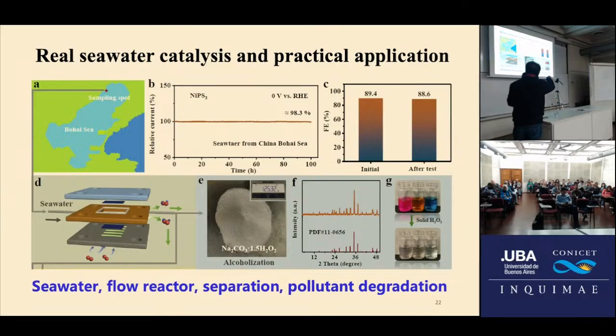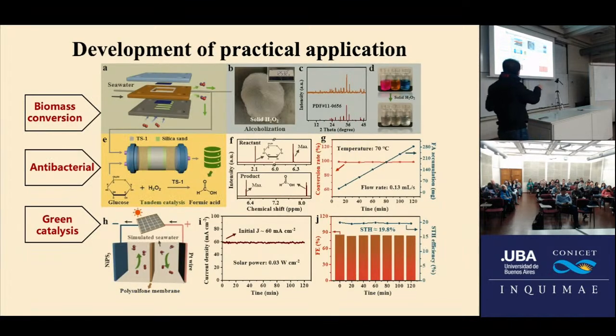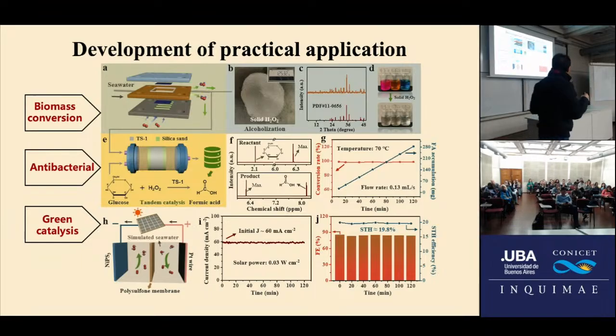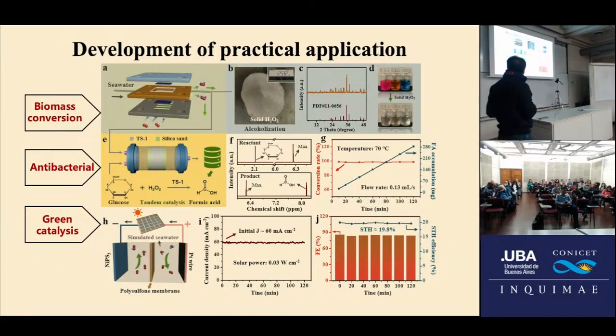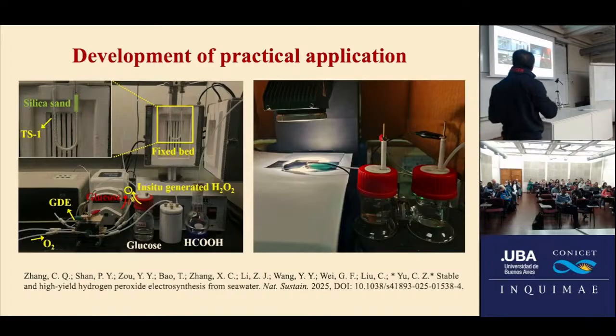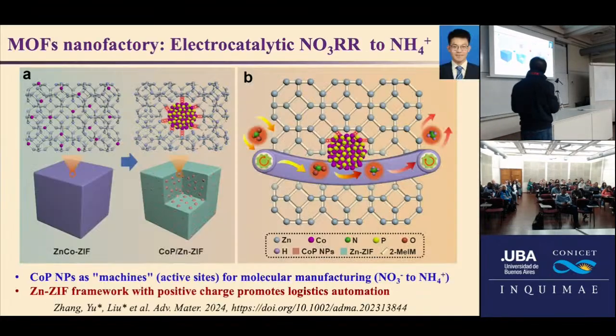You can regenerate this hydrogen peroxide and use it for dye reduction, and for in situ generation in applications, for example, oxidation of glucose into formic acid, etc. So this is one example showing that we could use a well-designed electrocatalyst and then use seawater for hydrogen peroxide production. We have also demonstrated that this system can be coupled with a solar panel for hydrogen peroxide production as well. I'm going to skip it here.